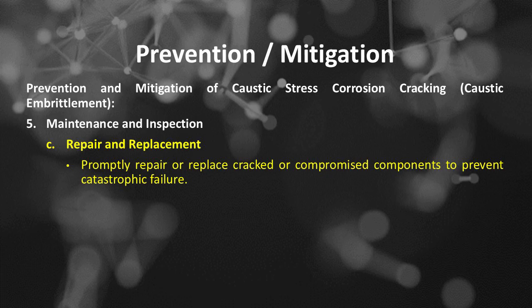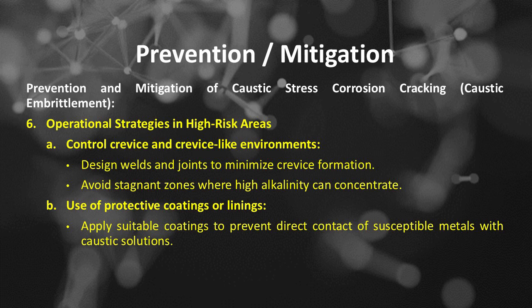Number 5 of prevention and mitigation of caustic stress corrosion cracking or caustic embrittlement is operational strategies in high-risk areas, which includes, number A, control crevice and crevice-like environments. Design welds and joints to minimize crevice formation, avoid stagnant zones where high alkalinity can concentrate. Number B, use of protective coatings or linings. Apply suitable coatings to prevent direct contact of susceptible metals with caustic solutions.